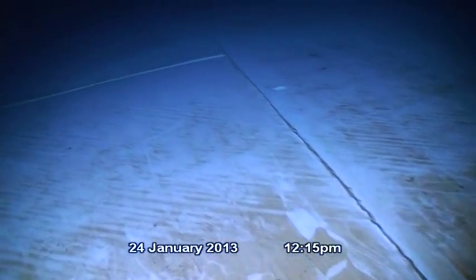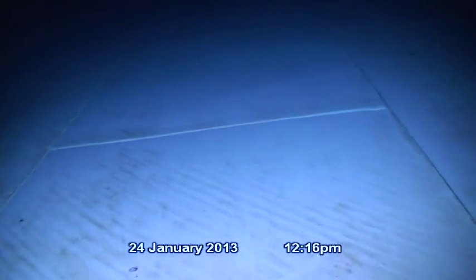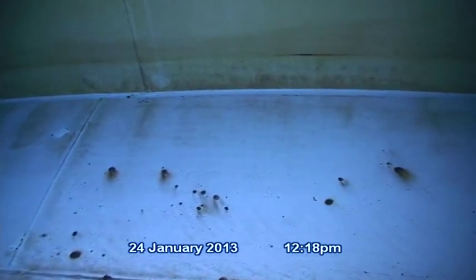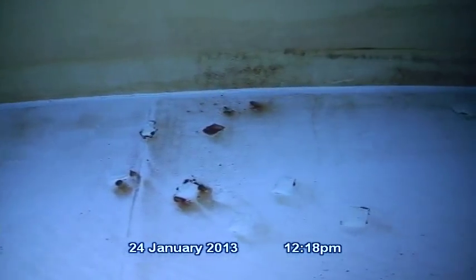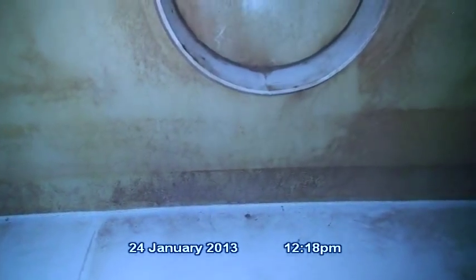The diver inspector is now swimming away from the center pole, documenting the removal of all loose sediment and debris. The floor is lightly stained in these areas. Pinhole type corrosion and very small corrosion nodules are present in thousands of areas on the floor. Here's a concentrated area of light surface corrosion and pinhole type corrosion. A few moderate sized corrosion nodules are located in this area near the transition from floor to shell. All the loose sediment and debris has been removed from this area.